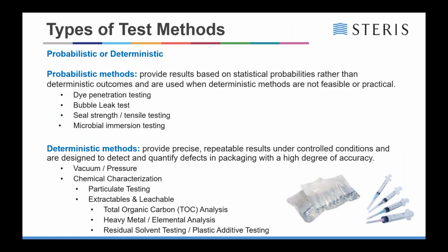There's lots of different types of tests out there, but if you look at the USP, what that actually does, it defines testing as both probabilistic or deterministic. Probabilistic methods provide results based on statistical probability rather than deterministic outcomes. And by that what it means is basically a lot of them are pass-fail. There's very little measurement in them. The typical test that we would do on packaging there would be the likes of dye penetration testing, bubble leak testing, or seal strength testing or tensile testing. Interestingly enough, tensile testing actually falls under both camps for a very specific reason.